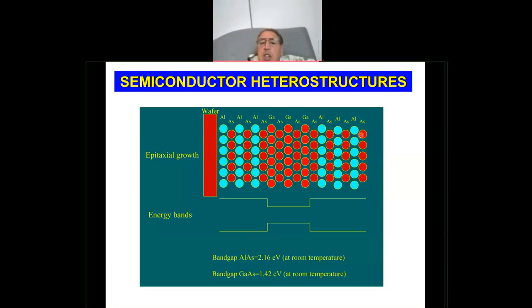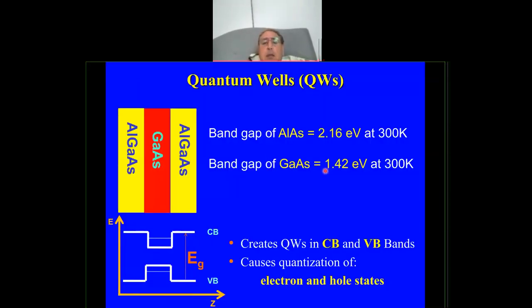But when you do this, you change the energy profile of the structure. So this is the physical structure, but this is the energy structure or profile of the device. Because aluminum arsenide has a very large energy band gap compared to gallium arsenide, by doing this sandwich structure, you form what we call a quantum well. As you can see, it's a well both for the electrons and for the holes. So this is the conduction band, and this is the valence band. And this just shows you, for example, the values of the band gap of these two semiconductors. So this is how we form these heterostructures. It's practically just putting materials one on top of the other, and then we can engineer this energy profile of the semiconductor. So what does it mean, for example, if you want to make a quantum well?